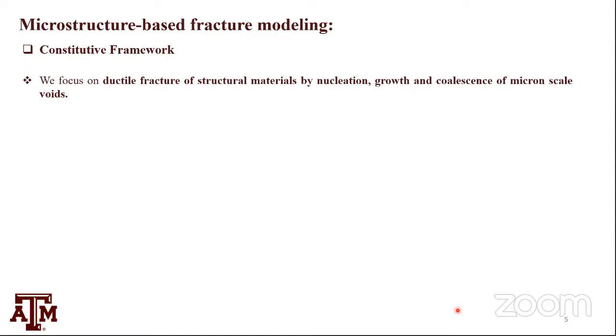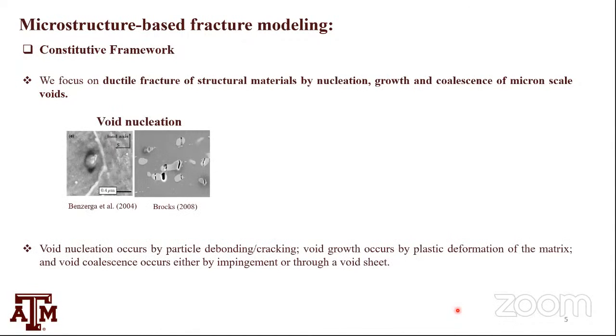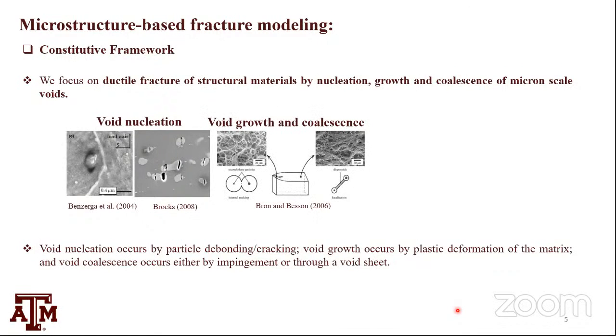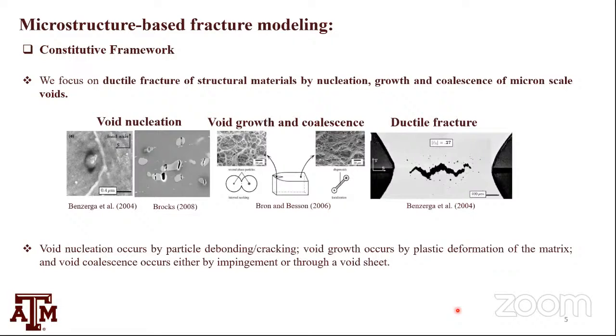So constitutive framework, basically we're going to rely on ductile. We're going to model ductile fracture. This is what I do. We're going to focus on void nucleation, growth and coalescence, and that leads to formation of a crack. So this is the basic premise. And how do we mathematically write it?